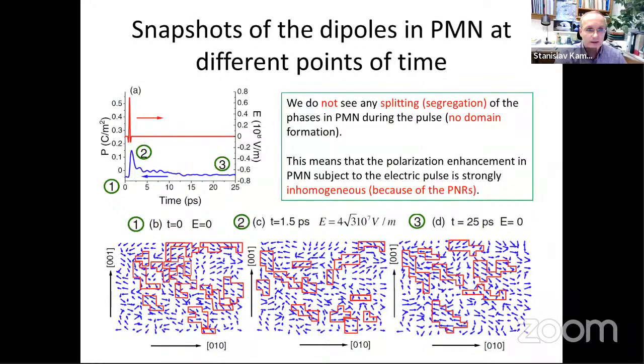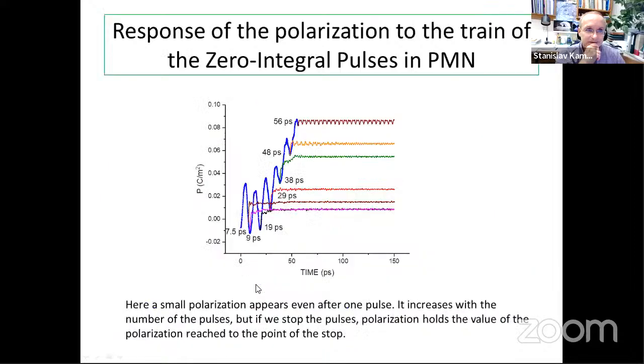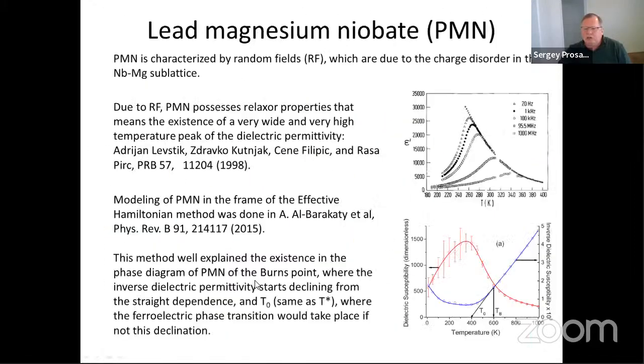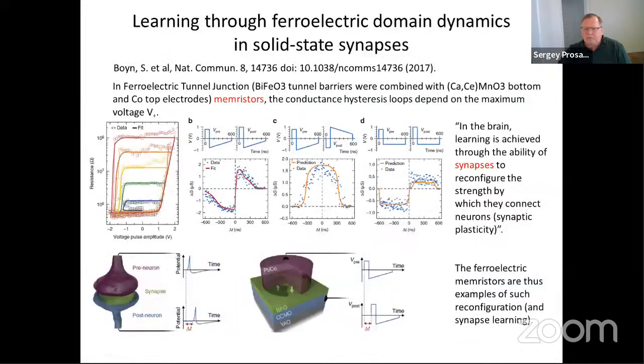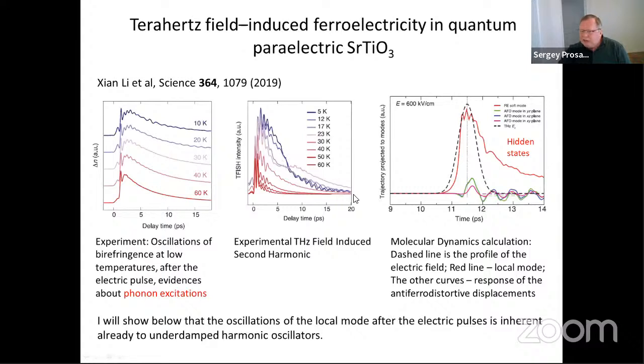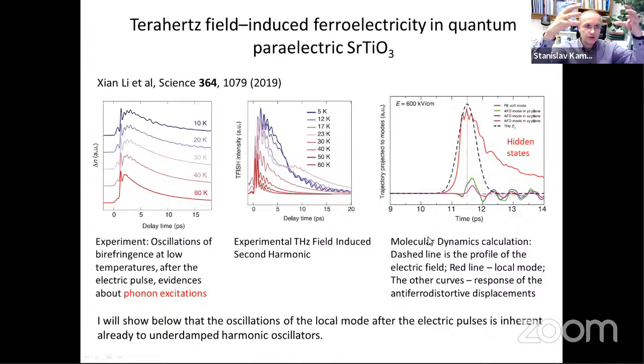You can say that in that paper, you see that the polarization is decaying and diminishes after the pulse. So this intermediate hidden state doesn't exist, say, after 20 picoseconds. Yeah. Here also we see it is constantly decaying. And the decay can be shown just in the harmonic oscillator model. So this is not... You excite the lattice, you change the structure on a picosecond time scale, and then it decays and goes again to the paraelectric state.